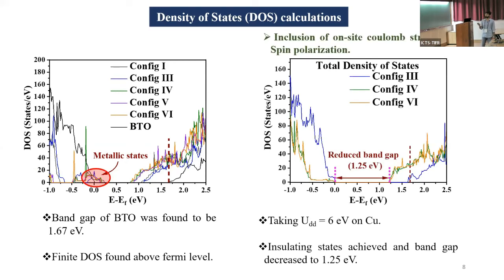And also, since the copper ion is a transition metal ion, it comes with an on-site Coulomb strength U_dd. So we chose U equal to 6 eV on copper following the literature. And what we found is that for the configurations studied, 3, 4, and 6, the band gap reduction was to 1.25 eV, right from 1.67 eV. So we have reduced the band gap now.